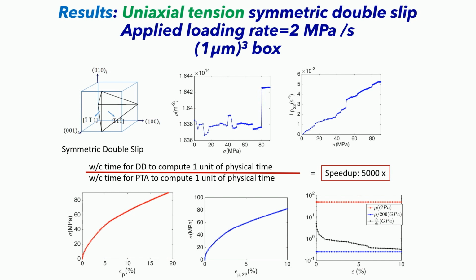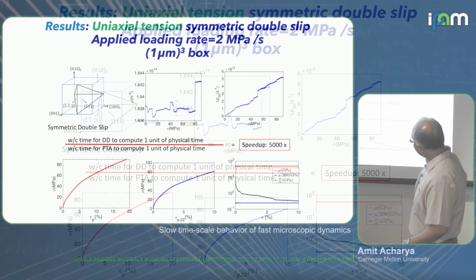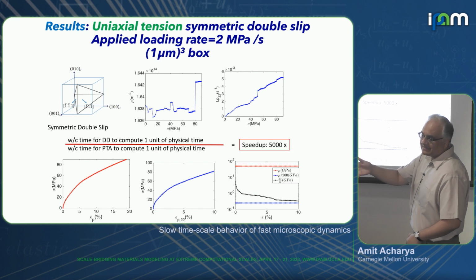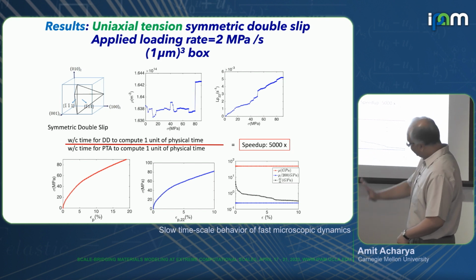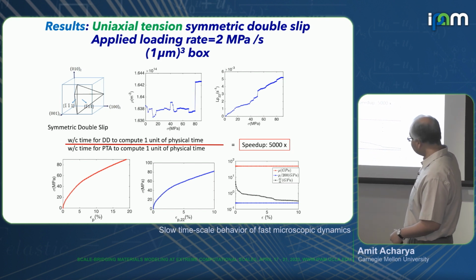When you do this, you realize that the stress is not obligated to even go in the right direction. Plastic strain may be happening in this direction. You're doing all this averaging. Stuff might be going in the other direction. Stress could be going negative too. So even this is in some sense a prediction, okay? You go up to 10% strain. You shouldn't go up to 10% strain with a small strain DD theory, but that's a separate issue. These are stress strain curves.